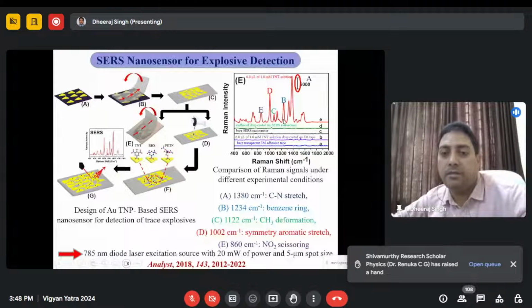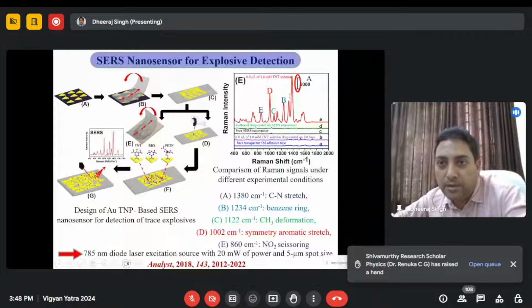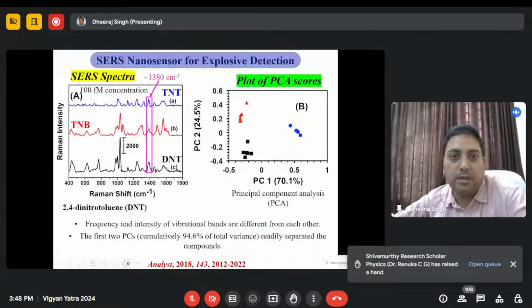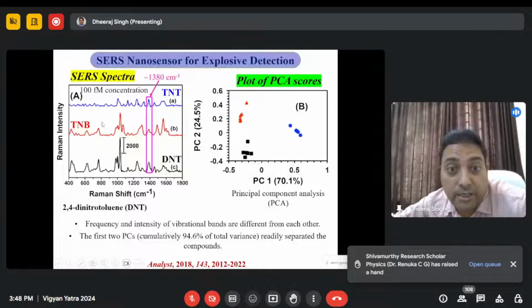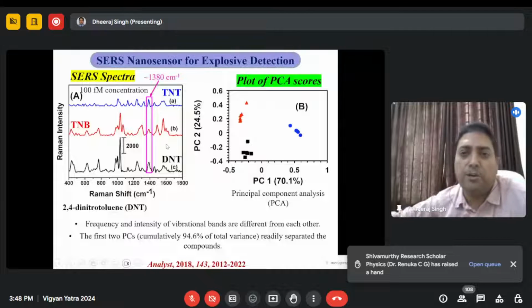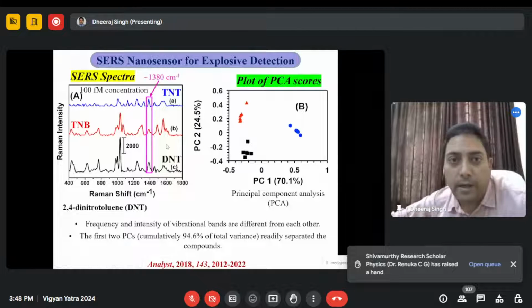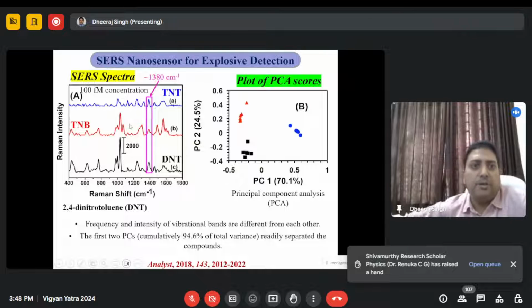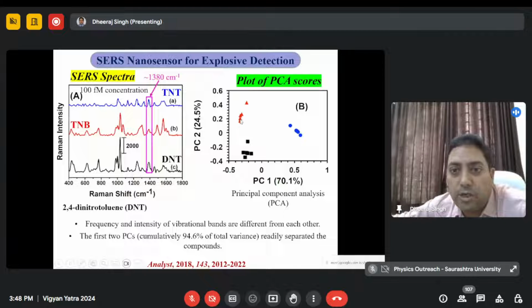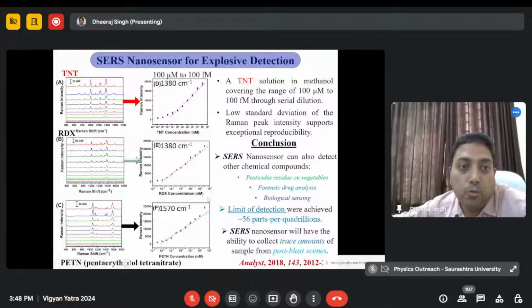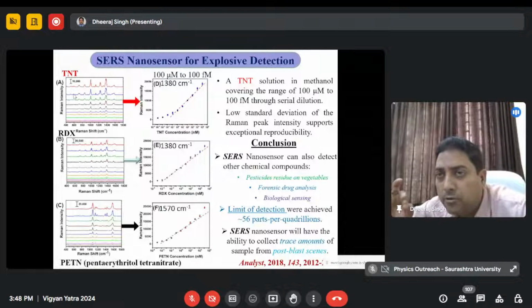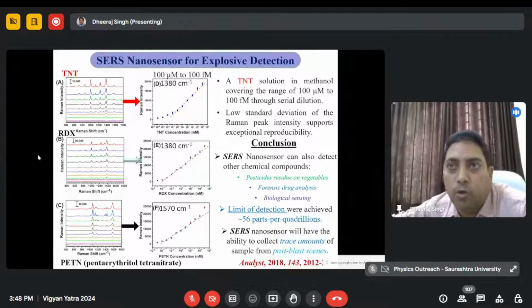It means the signal is enhanced in the presence of that, and identification of these A, B, C, D peaks is the clarification of that. Now you can see that TNT, TNB or DNT are all very similar types of explosive elements used by terrorists, and they are easily detected by this difference. Principal component analysis clearly identified that there are 3 different compounds. So by Raman spectroscopy, we can also see the difference between RDX and this. So now we can see RDX and TNT even at lower concentration, 10 to the minus 12 molar, means a small quantity of TNT or RDX dissolved in the liquid phase.